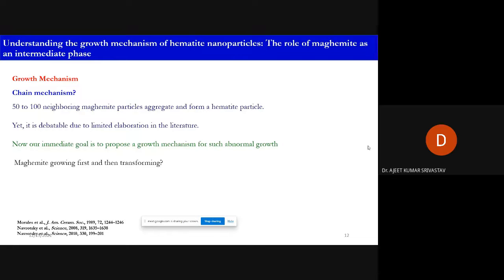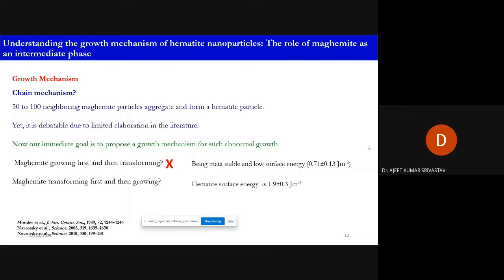But for that, the first thing we should talk about is whether maghemite grows first and then transforms, or maghemite transforms first and then grows. So if we see that maghemite has the lower surface energy and it is metastable as well, okay? Why? Because the hematite surface energy is on the higher side, okay? So hematite is not going to be stable at such very, very fine sizes, because of the higher surface energy, okay? So with this argument, we can say that maghemite transforms first and then grows, okay? So it means that hematite seed formation happens, and then the transformation proceeds, and further then growth happens, okay?